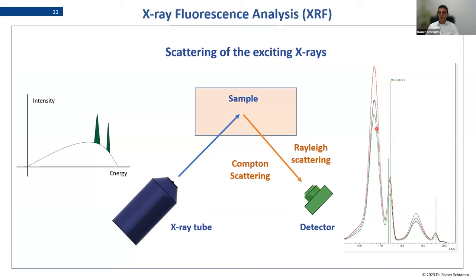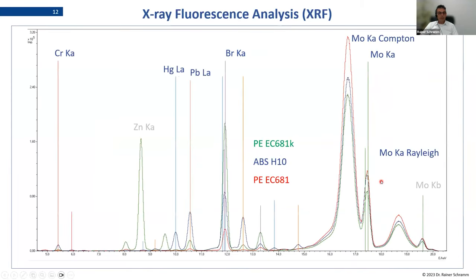And the interesting point here is that the scattering effect is directly correlating with the sample composition. So that means the elements of the samples make different scattering. So this peak will always represent what elements in total are in this sample. And this means that we can use that peak like an internal standard to correct for the whole sample, so for the matrix effect of the whole sample. And this is an example. I have here two materials, polyethylene and ABS, so two polymers, and in total three samples.